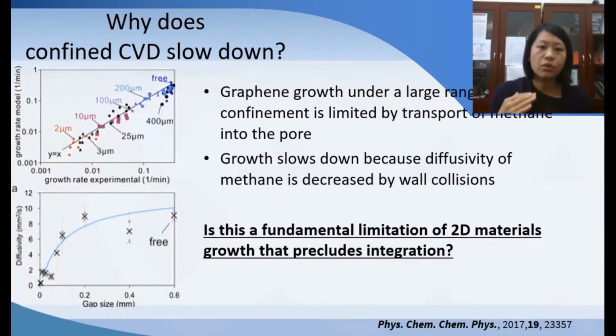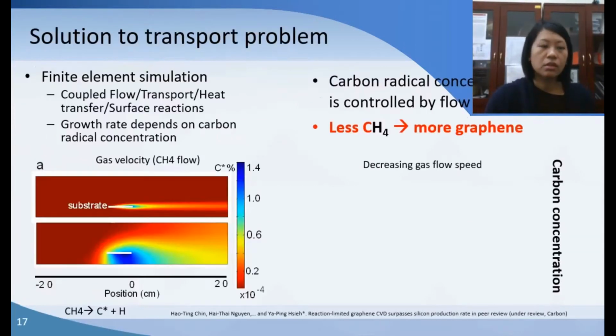So the whole thing, the confined synthesis, the growth rate here can be simply explained by how precursor is diffused into this confined space. So we found that the diffusivity is dominating the growth rate, and so it's also completely correlated to the gap size. And so we were wondering how come it's so slow, and so we did simulation, because it doesn't make sense to us, it's way too slow.